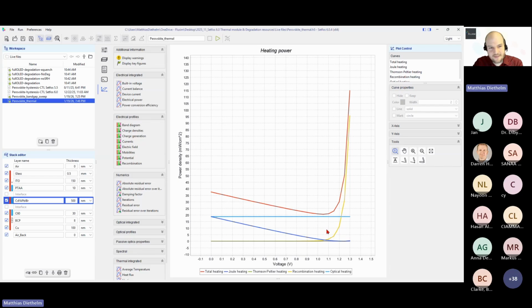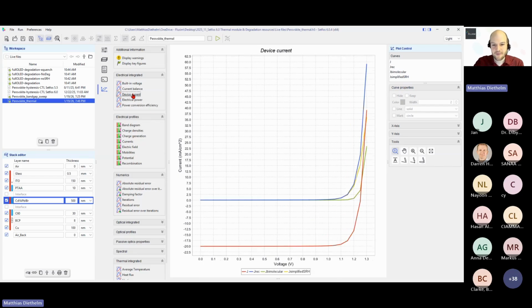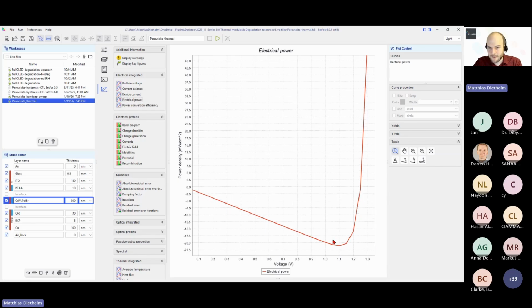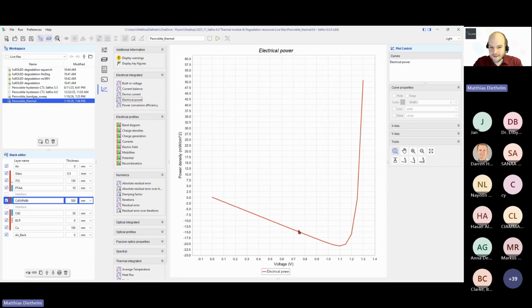And just to understand this curve better, if we look at the device current here, the simulated one, if we go from the maximum power point towards short circuit, for example, you extract less and less energy. So if we look at the electrical power with the maximum power point here, if you are at short circuit or at VOC, you don't extract any energy anymore, which means in turn that this energy must be again dissipated in heat.